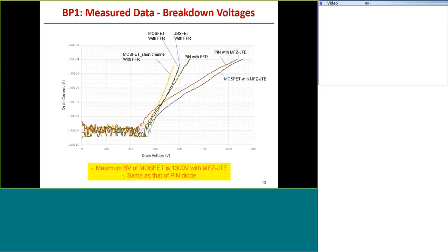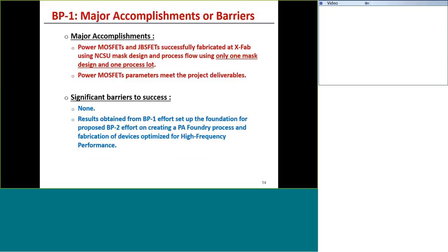In contrast, if you change the termination to the MFZJTE, then the breakdown voltage improves considerably, and we can meet our design target of 1200 volts. So it is important that we use the MFZJTE termination. The FFR (floating field ring) termination we found did not work as well as the MFZJTE. The fact that the PIN diode has the same breakdown voltage as the MOSFETs indicates that it is the termination that's limiting the performance.